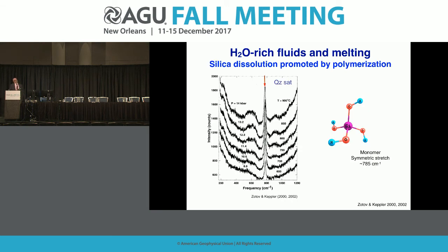Experiments that have been done on this system some years ago now in a hydrothermal diamond anvil cell showed that as you raise temperature and pressure at quartz saturation, the water acquires more and more silica. And if you do Raman spectroscopy, you see that there's a very important large peak here, which corresponds to the stretching mode of the silica monomer. But you can see that as temperature and pressure rise from the bottom spectrum here to the top, there's a growing intensity in this region and in this region right here, which correspond to the silica dimer. The silica is polymerizing as pressure and temperature increase. You're forming bridging oxygen positions, losing an OH, and this is being expressed by the growth of the intensity in the Raman spectrum.